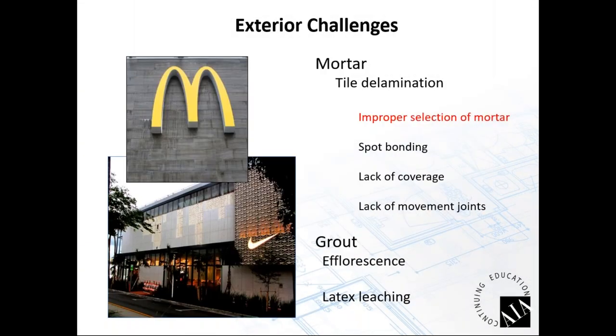So, some of the challenges when we start looking at doing exterior work. So we see a tile delamination, in other words, tile coming off the building. What's happened here? Did we have an improper selection of mortar? Did we just use a basic ANSI A118.4 mortar, put this tile up onto the wall, and now all of a sudden we have a freeze thaw condition and the tile starts popping off the wall?